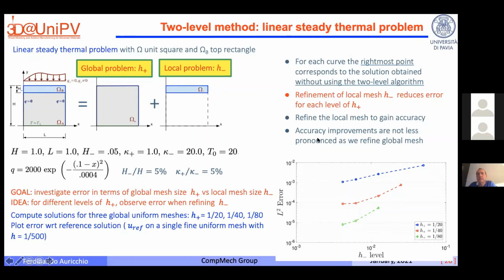The very nice thing from the numerical point of view is reported in this picture. What is this picture showing? It shows that if you fix your global mesh and you refine only locally, so you fix the mesh on this domain and you refine the mesh only here, you always get better behavior. So if you have phenomena which are very local and you want to describe them better and better, you don't need to refine the mesh everywhere, but only in the local region. Okay? And that's what these numerical results show.